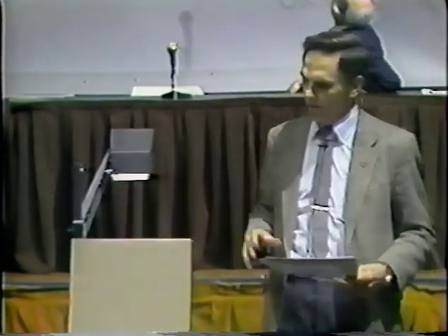Now, this is a summary of a sequence of processes and events that will lead to cold nuclear fusion. First, you must prepare the electrode, which means clean the surface, purge the interior of any poisons, unwanted isotopes, and that could involve annealing, of course. The second element is the deposition of deuterium at the surface of the electrode. This, of course, involves the process of electrolysis. But now, once the deuterium is on the surface, it loses its electron to the interior. The electron is stripped off, goes in the conduction band of palladium. This leaves a nucleus, essentially a bare nucleus, on the surface, which diffuses to the interior.